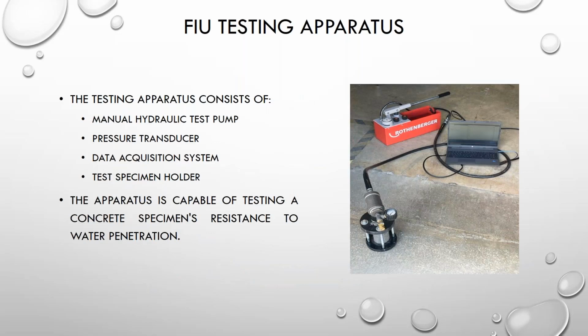The FIU testing apparatus consists of the hydraulic pump, you can see over here, the pressure transducer, the data acquisition system, and the test specimen holder. The testing in this configuration is set up for a cylinder, but this can also be used for flat surfaces such as pillars and other concrete surfaces. The apparatus is capable of testing the concrete specimen's resistance to water penetration.